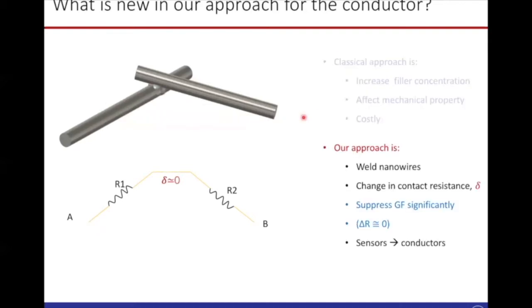Now we propose a different approach by programming the microstructure or nanostructure of this conducting nano network through welding. By welding, you can eliminate this contact resistance. Also, you can put some constraint on the slippage in most of the nanomaterials. So as a result, we propose we will be able to suppress the gauge factor or control the change in resistance. In that way, the sensor-like behavior could convert into a conductor-like behavior. And we expect both sensor and conductor could be fabricated from a single material.